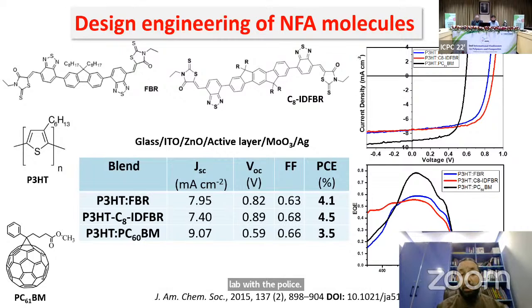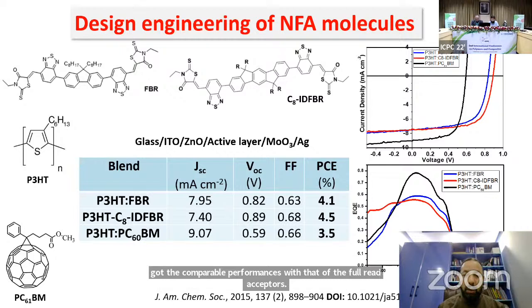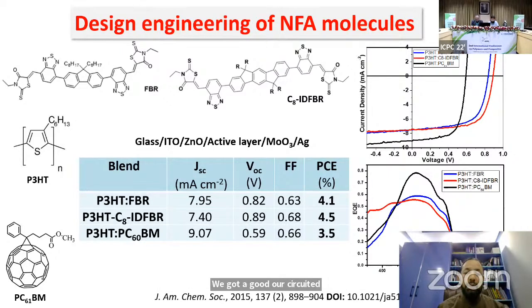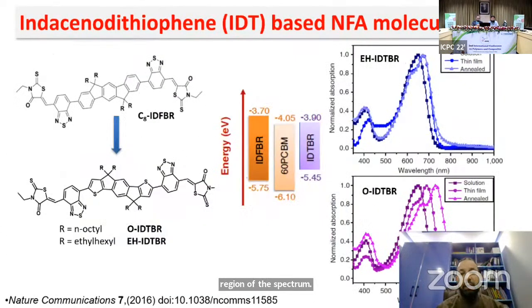For our initial designs, these two non-fullerene acceptor molecules, we got performances comparable to those of the fullerene acceptors. We got good open circuit voltage, but we had limited photocurrents, because these non-fullerene acceptor molecules were still not absorbing enough in the visible region of the spectrum. So we went back again in the lab and decided to modify the structure of the non-fullerene acceptor molecules.